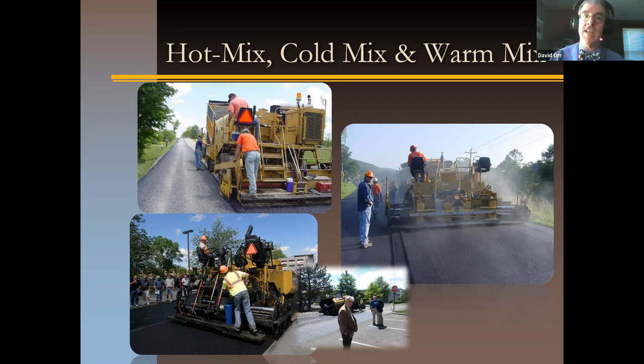That's one way to make asphalt a liquid. Another way to make it liquid is to heat it up a little bit, in the mid hundreds, upper side of that, and mix it with water, or they used to actually use gasoline and diesel fuel, cutbacks and things like that, and make a colloid like a salad dressing. You make a liquid out of it and you can get a pretty good mix. Cold mix, I like cold mix. It's got some real advantages in some places.